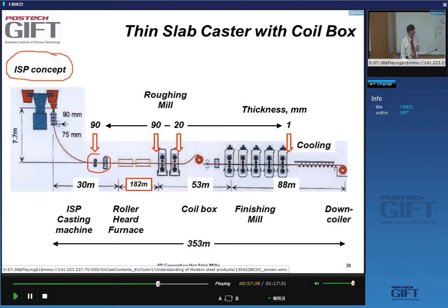For instance, one of the things you see is that there is a soft reduction of the strip. Soft reduction is when the material comes out of the caster, the central part of it may not be fully solidified. And what the soft reduction does, it squeezes out the last remaining liquid, so that you reduce the amount of segregation in the center, and also avoid porosities in the center of this thinner slab.